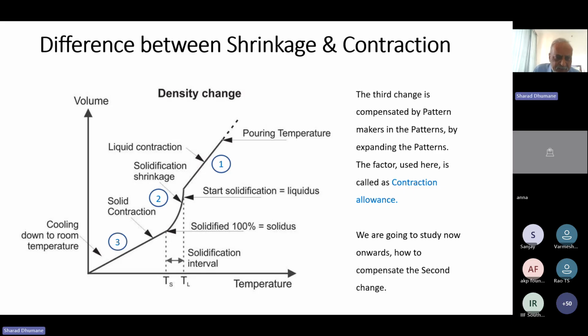Okay. So at here, this particular reduction in volume we compensate by adding a contraction allowance in the patterns. So when the patterns have been designed with an appropriate, accurate contraction allowance, then this particular volume decrease has been fully compensated. So we get our casting to the dimensions which are desired by the drawing. So this particular part we take action, we resolve this particular volume contraction.